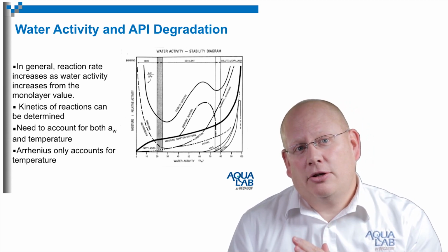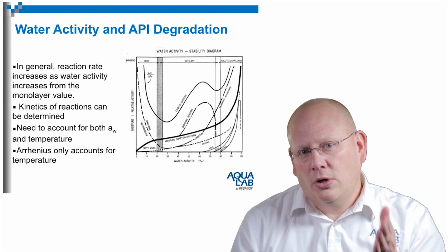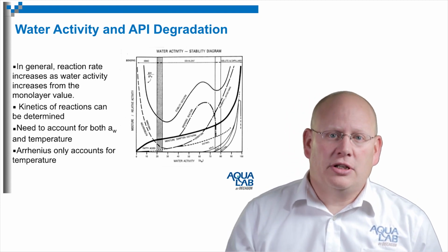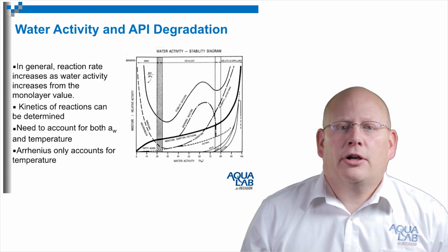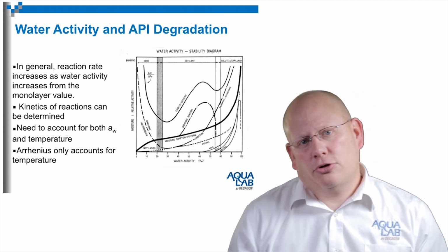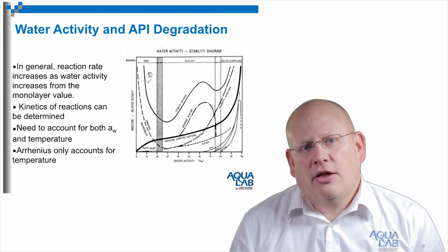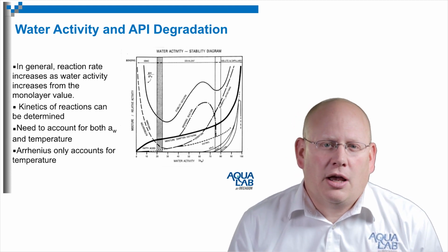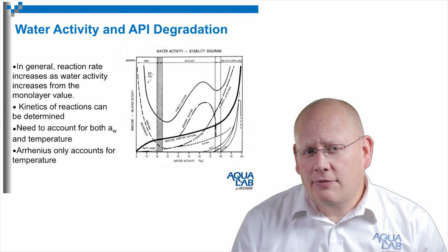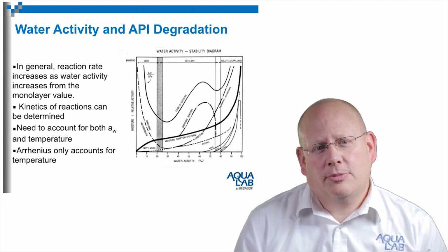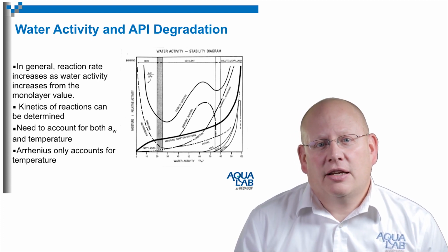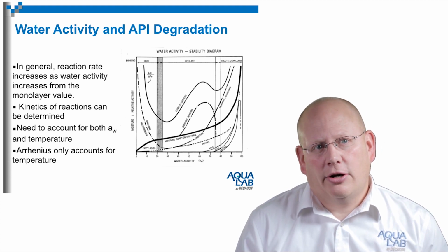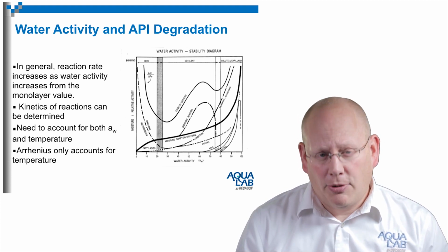The rate at which that increases, again, is specific to the material itself and the reaction, but it can be modeled using some experimental work where you look at several different temperatures and water activities and track the progress of a reaction, combine that information, and using Q10 values and a combination of those, it's possible to actually model the kinetics of those reactions according to the effects of temperature and water activity. But water activity does have to be part of it.